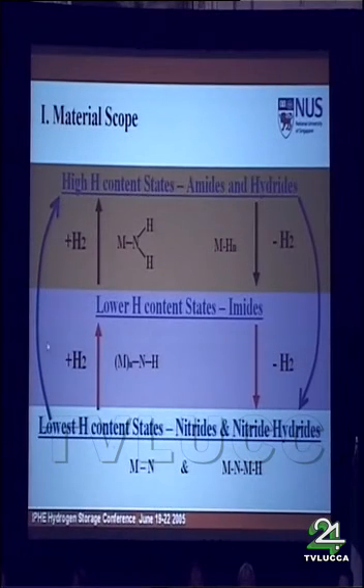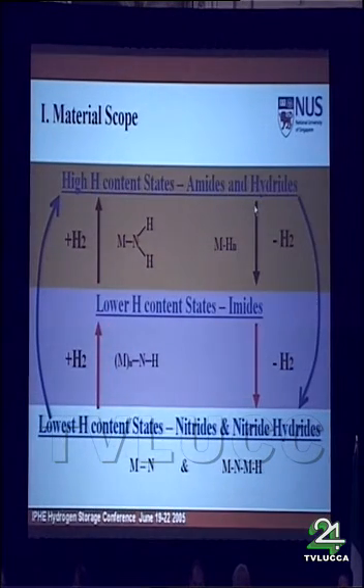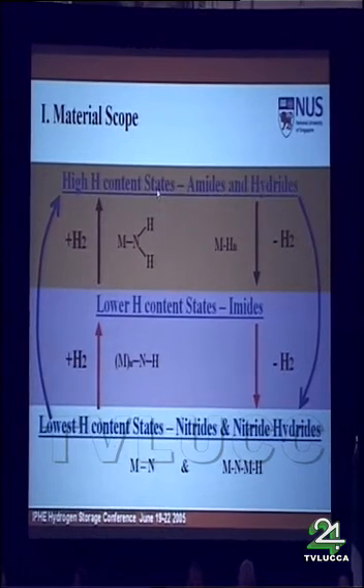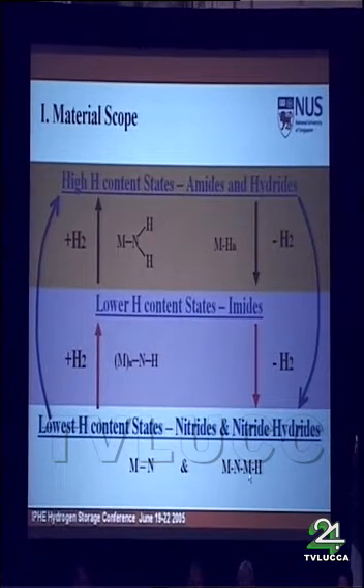So first of all, let me introduce the material scope for the metal nitrogen hydrogen system. If we divide the system according to the hydrogen content, we can see there are 3 states. High hydrogen content states, which include amides and hydrides, low hydrogen content states, which normally are imides, and lowest hydrogen content states, where we normally encounter the nitrides and nitride hydrides. You can find the difference between the imide and nitride hydride. In imide, hydrogen bonds with nitrogen, and in nitride hydride, hydrogen bonds with metal. These are two different chemicals.